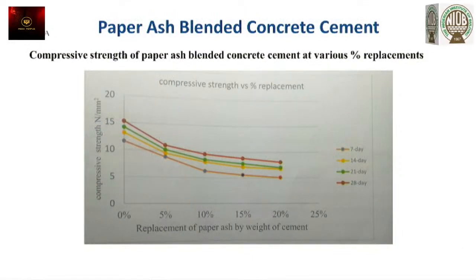Now, this waste paper ash was used in this research to substitute for Portland cement in the production of concrete at various percentage replacements ranging from 5% to 25%. The mix ratio that was adopted is 1:4, and a water-cement ratio of 0.5 was used in this research. As you can see from this graph, for the various percentage replacements of waste paper ash in the concrete, you can see the strength development for 7 days, for 14 days, for 21 days, and 28 days.